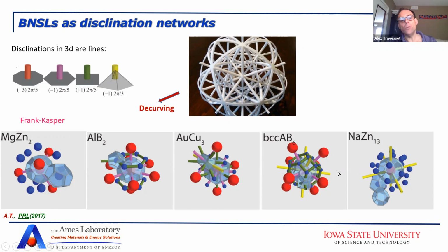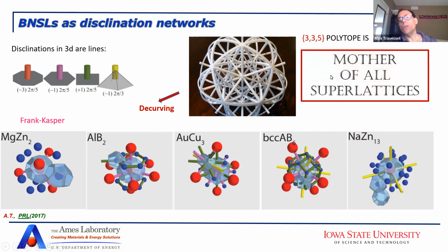And in this way, you are able to see that all phases that have been reported experimentally actually happen to be networks of disclinations from the 335 polytope, in what we could call quasi-Frank-Kasper phases. So in a way, the 335 polytope is kind of the mother of all superlattices, in a way that if you start with this, by adding disclinations, you can build all these other cases that experimentally have been found.